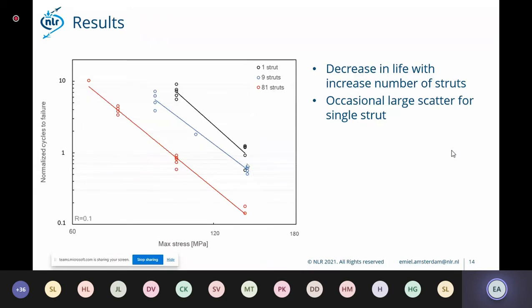To investigate if the life decreases with the number of struts or if it's an effect of the diameter, what we did with the 9 strut specimen: we took one 9 strut specimen and we removed the individual struts from this geometry, and we tested those as single struts. So instead of the one strut geometry which has a 9 mm diameter, we used single struts from the 9 strut geometry, which have a diameter of 3 mm. Here you can see the result.